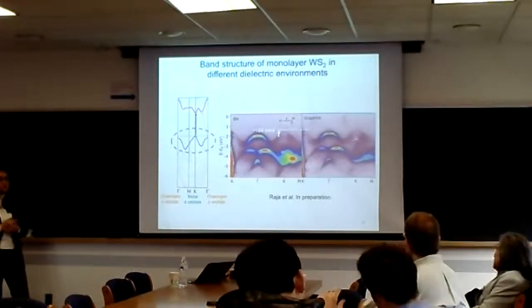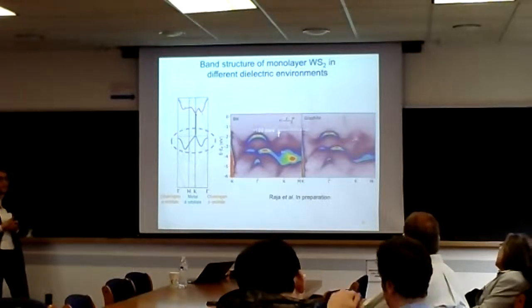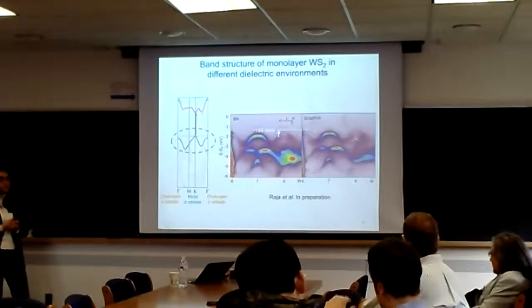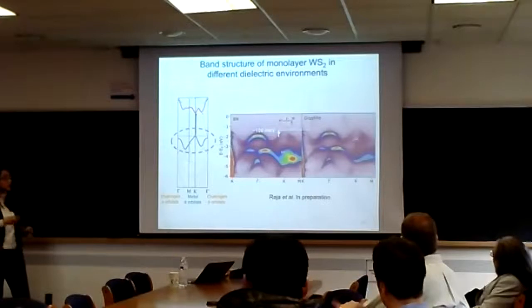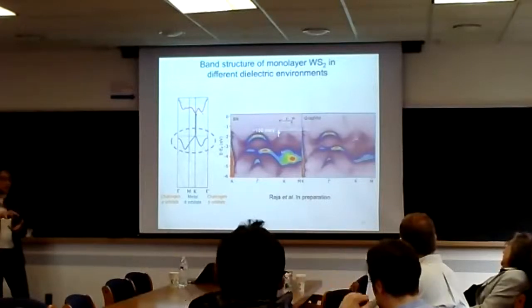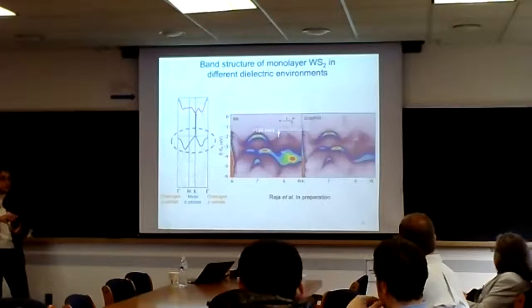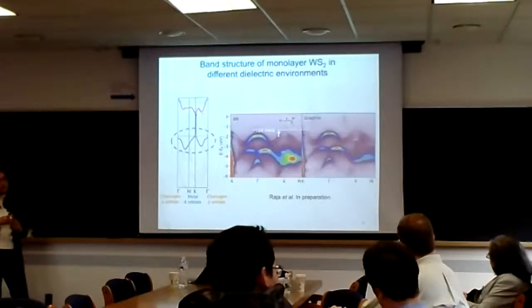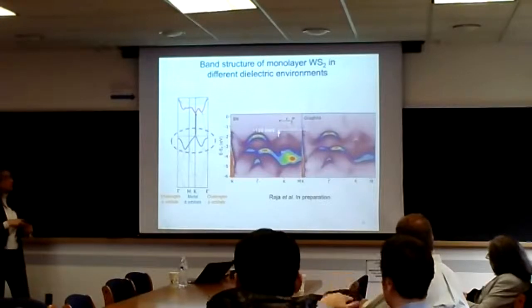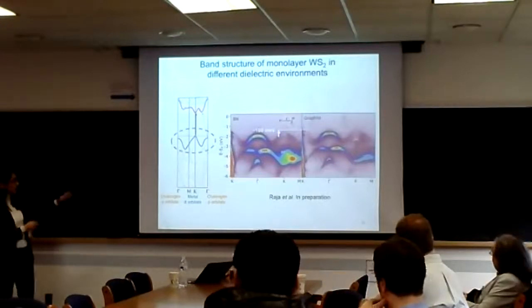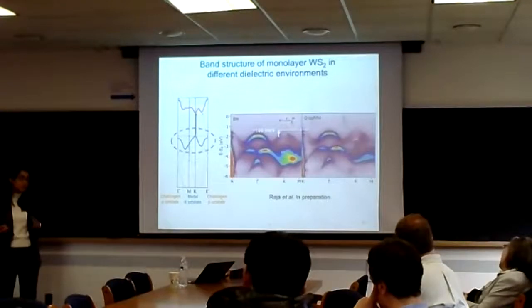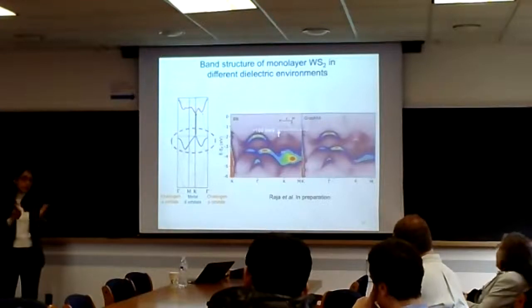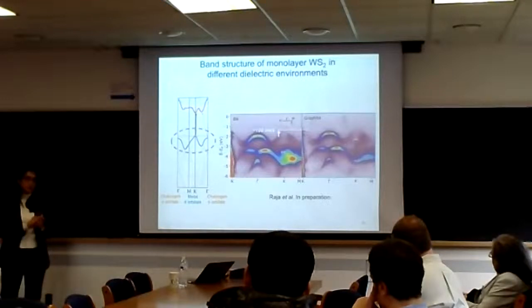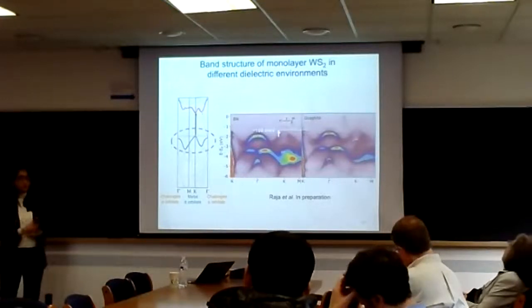And the fact that you cap only from one side as opposed to the other side, does that screen the exciton efficiently, or would it be better to have it on both sides? If you had it on both sides, you'd have more screening. I see, this is true. So what's the difference between two caps and one? I have some data in the backup that I can show you, but basically it would be another 50 meV. Say you were to encapsulate the whole thing with graphene, one layer of graphene on one side, one layer on the other side. You get more than 200 meV of renormalization, whereas on just one side you are closer to 150 meV.